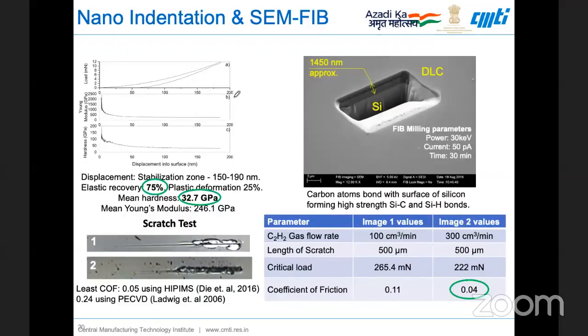The hardness value of what CMTI has developed is a mean hardness of close to 32.7 GPa, and the coefficient of friction goes down to as low as 0.04. This is to show how the coating looks. This is silicon wafer until here, and beyond this is diamond-like carbon. These are the two layers of coating, and you can see how well the interface is, you will not find any sort of gap over here. It's atomically bonded.